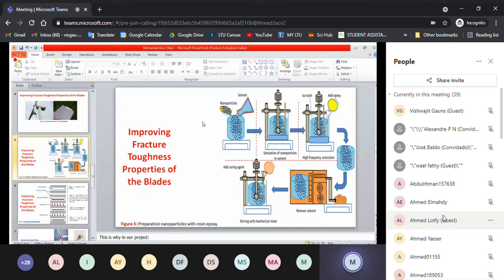This is why in our project we modify the blade's material by adding nanoparticles inside the polymer matrix composites that is already reinforced by hybrid carbon and glass fiber reinforcement. In this work we are going to use the compression molding technique. As we can see in this figure, in the current slide we suggested mixing nanoparticles such as alumina and graphene nanoplatelets with epoxy, or inside epoxy, to reinforce the plates.